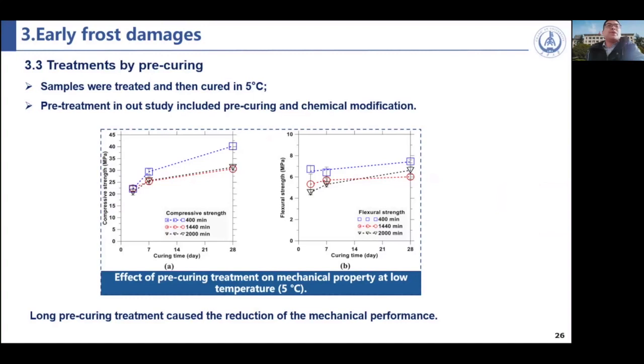So this is the effect of pre-curing treatment on the mechanical properties of the cement paste. We can see the longer pre-curing treatment will cause a reduction of the mechanical performance. This is not as we expected before we carried out the experiment. We thought higher temperature curing would bring higher strength, but in our experiment, we found that higher curing temperature brought lower mechanical performance.